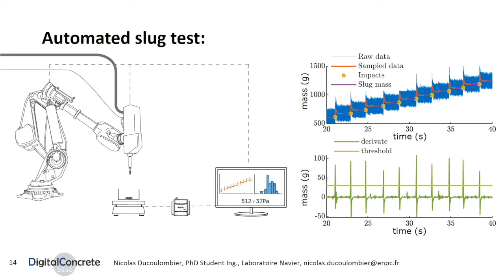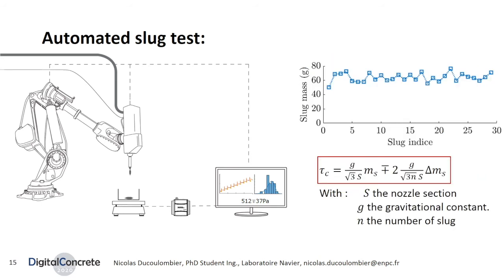An appropriate discrete derivation of the signal and a filtering procedure then permit detecting the slug impacts. More technical information is provided in the respective conference paper. The difference between each step gives the mass of each individual slug, which is plotted on the following graph. Both yield stress mean value and confidence interval can then be automatically calculated using the same expression as the one obtained for the manual slug tests, taking the number of experiments k equal to the number of slugs n. This automated slug test, using our printing head equipped with a 20 mm diameter nozzle, was used for the second part of the experimental validation. The number of slugs n is around 30 for both manual and automatic slug tests.